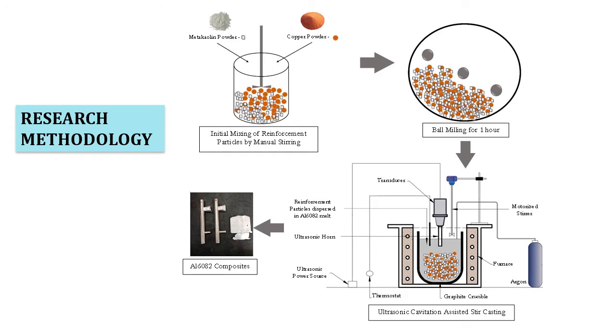The author has already worked on composites reinforced with Metakaolin powder and observed that there is a reduction in ductility. So in this particular study, the author has mixed the Metakaolin powder with copper powder, and the mix has been reinforced on the aluminum matrix. So the functionalization, the mixing has been done by initial stirring followed by ball milling, and the premixed powder has been subjected to the aluminum melt, and the composites have been prepared. The details are available in the manuscript.